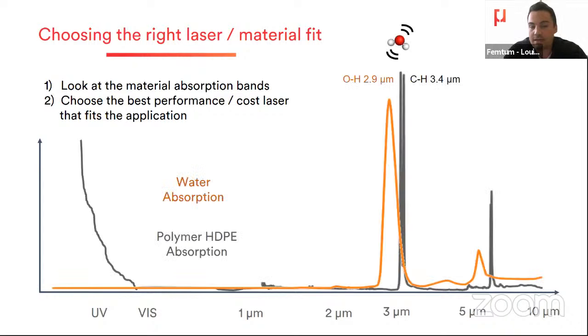I plotted 2 examples here, water and 1 polymer, high-density polyethylene, HDPE, and you clearly see that the highest absorption bands are located in the neighborhood of 3 micron in the mid-IR, and that's where basically you find the fundamental vibrational modes of water and hydrocarbons, so at 2.9 and 3.4 micron respectively. And you also see that there's other types of absorption, so in the UV or deeper in the mid-IR, so at 5 to 10 micron.